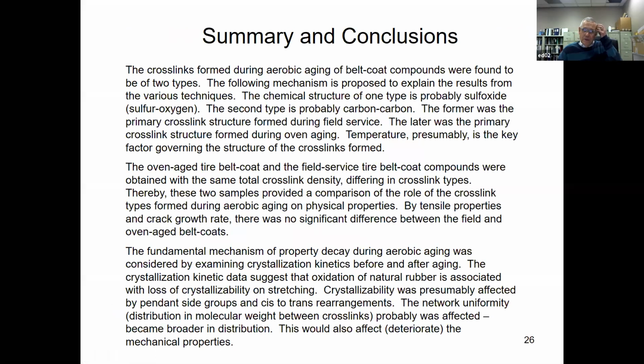So in summary of the first part, we said the crosslinks formed during aerobic aging of the belt coat compound were found to be two types. The following mechanism is proposed to explain the results from the various techniques. Chemical structure of one type is probably sulfoxide, sulfur-oxygen linkages. The second type is probably carbon-carbon linkages. The former was the primary crosslink structure formed during field service. The latter is the primary crosslink structure formed during oven aging. Temperature, presumably, is the key factor governing the structure of the crosslink